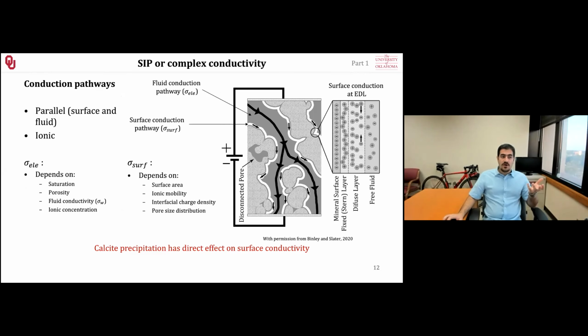Based on that, we are able to measure a lot of different features because electrical conduction through the pore-filling fluid depends on the saturation. If we have a partially saturated soil sample, we have a different conduction. If we have a dry sample, a different conduction. And if it's fully saturated, a different conduction. It depends on the porosity. The more porous it is, the more interconnected the space that we have, the better the conduction, as well as depending on the fluid conductivity, if you have a very saline solution or not a saline solution, and so on. So basically the ionic concentration is important as well.